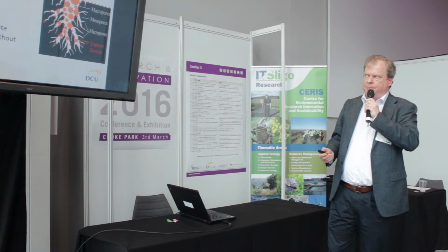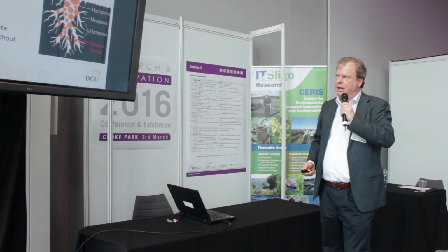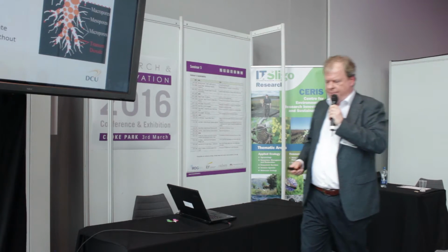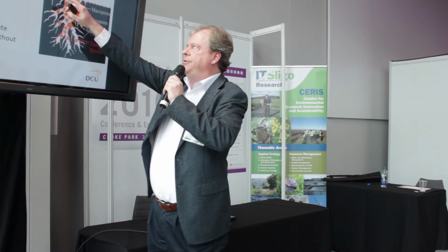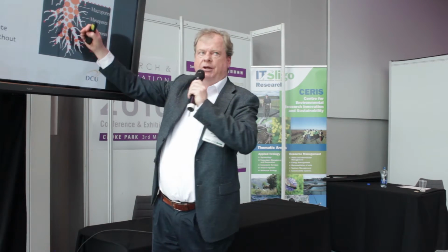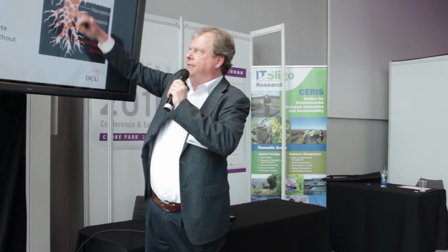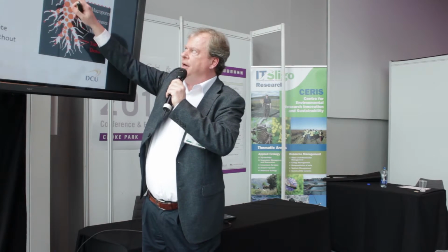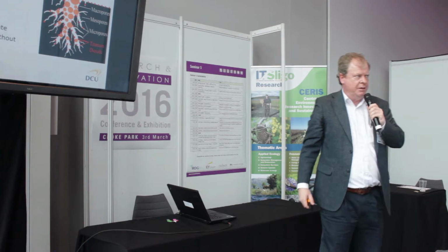So we spent quite a bit of time developing these types of composites. Most of it is now in the literature that we've published. Through simple techniques, whether sonication and/or thermal techniques, we can readily control the amount of titanium dioxide that we put onto the surface, as represented by these red dots, okay? So again, the idea is you get adsorption, and when the activated carbon is saturated, you then irradiate with light. Of course, there's always mass transfer occurring with your pollutant. It generates hydroxyl radicals and destroys the pollution, cleaning your activated carbon, and that way it can then be reused again.